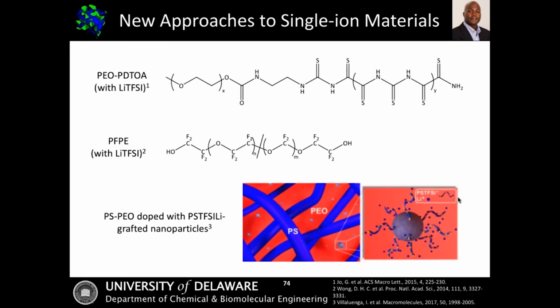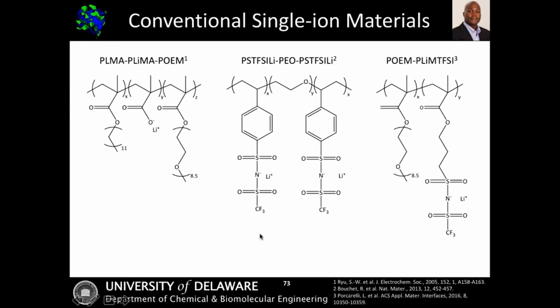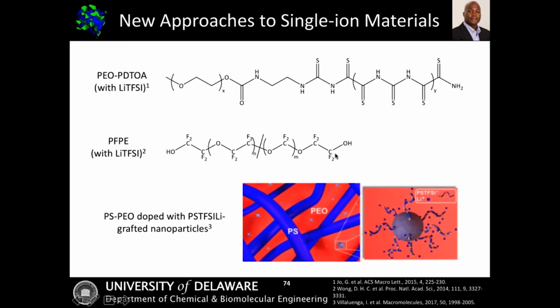So one is that these materials that I've shown here end up being quite synthetically challenging, right? They're not as simple as just a conventional PS/PEO or even some of the brush materials that were shown previously. Now I can move to other types of systems where I don't necessarily have a single ion per se, but I can start doing things like where I dope with a lithium salt here, in this case lithium TFSI.